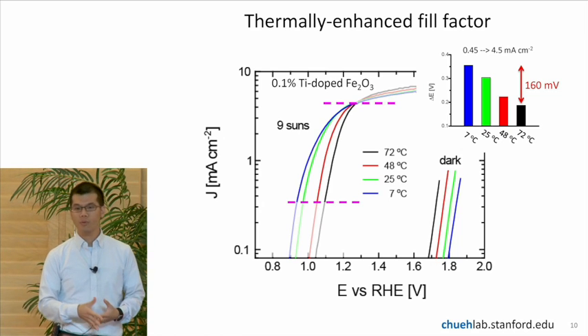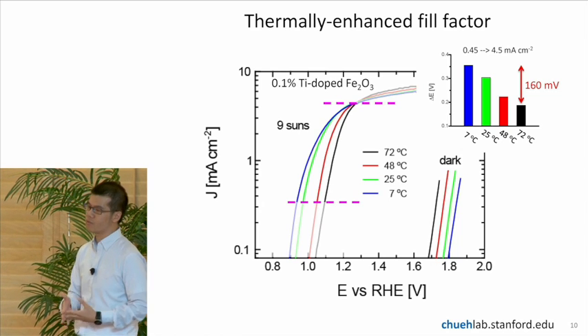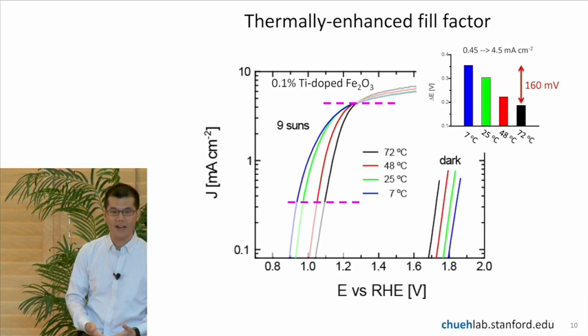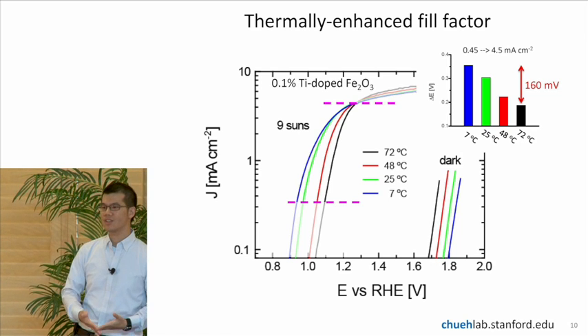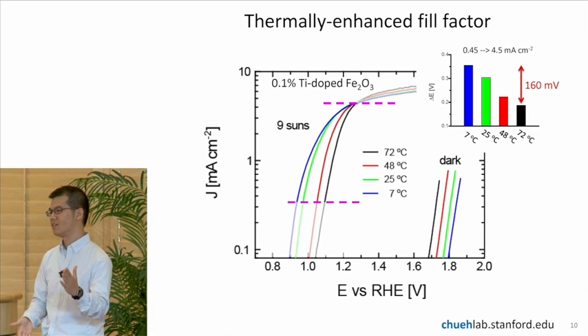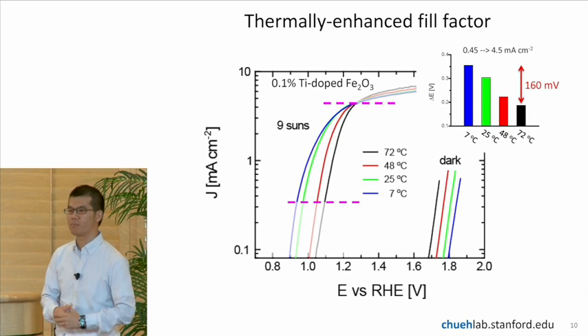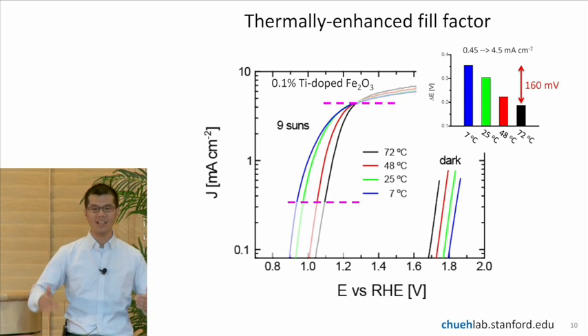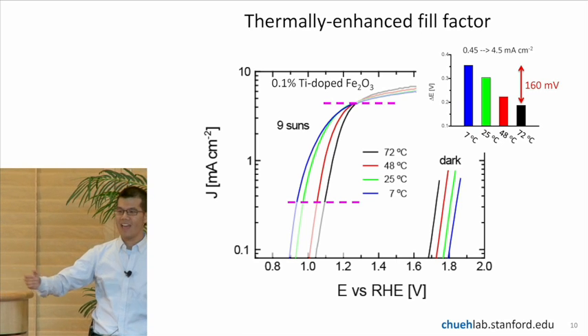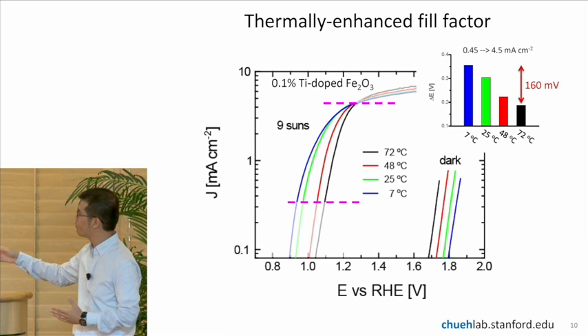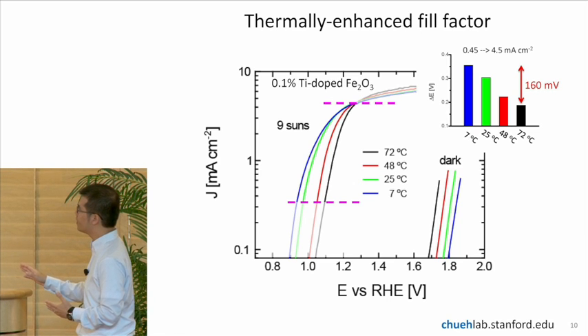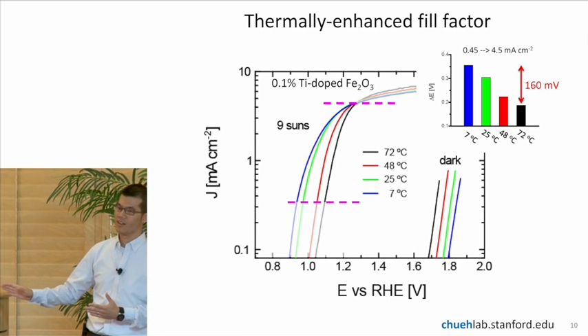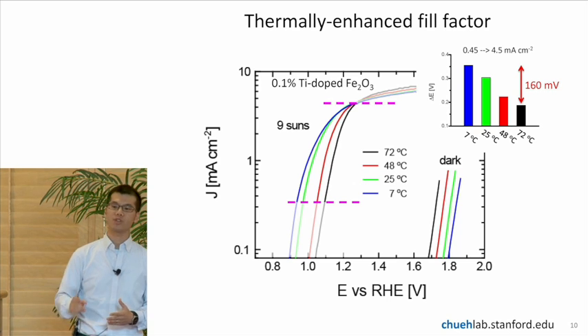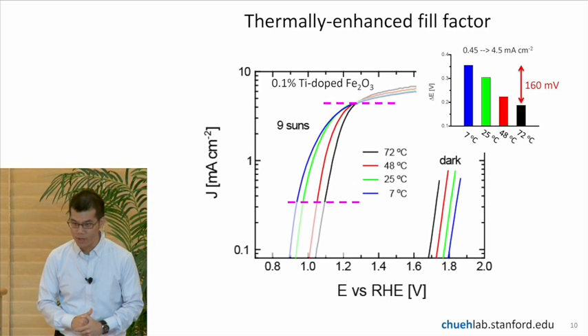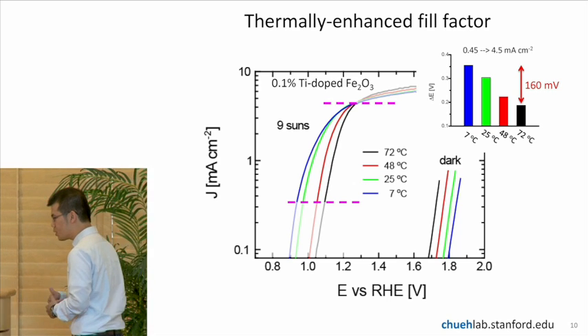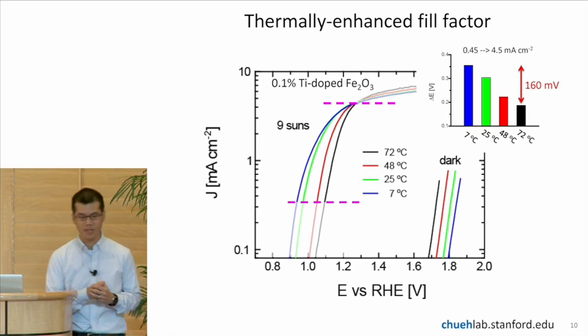For those familiar with solar cells, one of the key characteristics of solar cell is the so-called fill factor. The fill factor basically tells you how fast your current increases with potential. Ideally, we want something kind of like a square rather than a slanted line on this curve. And what I'd like to point out to you is the current actually rises much faster with potential when you increase the temperature. And I can show you this better by blocking out some of the data.